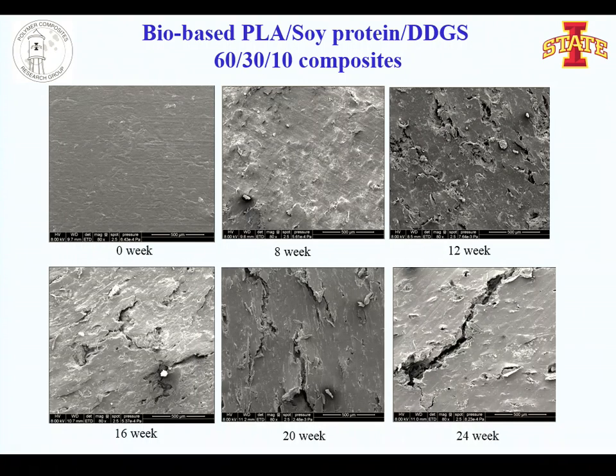And this is again the surface morphology of the composites. It's a very smooth structure here, and a very deep crack has been observed after 24 weeks.